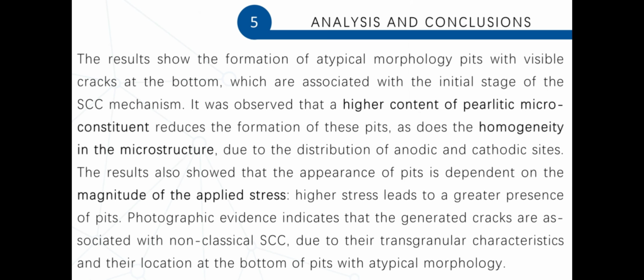So finally, what were the conclusions and analysis we made for this study? Well, the results show that the formation of pits with atypical morphology with cracks observed at their base indicates the initiation of the stress corrosion cracking mechanism. It was also observed that a higher content of pearlitic microconstituent and greater homogeneity in the microstructure reduced the formation of these pits. Additionally, it was found that the magnitude of the applied stress directly influences the occurrence of pits, with a higher frequency at greater stress levels.